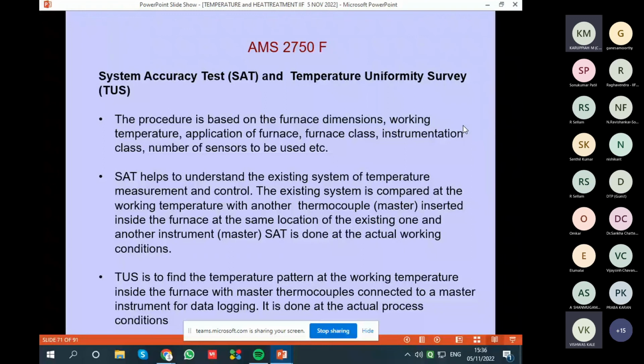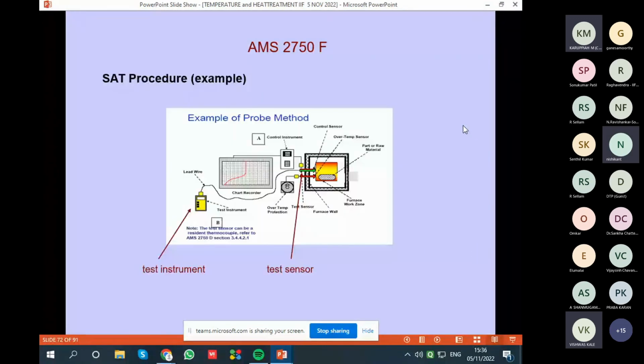See, you can see here, there is a test instrument which is independent of the furnace. There is a test sensor which is independent of the furnace, and we measure the temperature on the test instrument along with your instrument on the furnace. So we don't disturb your process. We measure it independently and just ensure that the test instrument where I measure and the test instrument which you have, that they are matching or whether there is any variation. This is called SAT test.